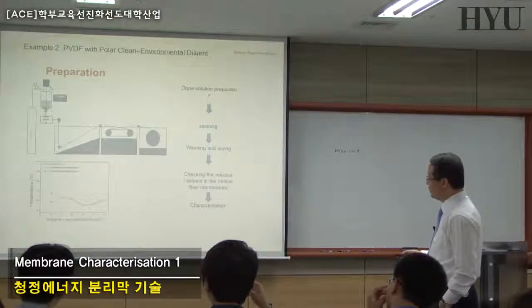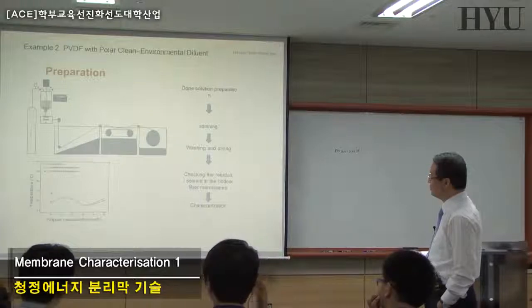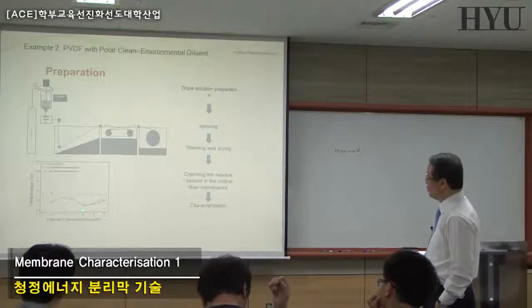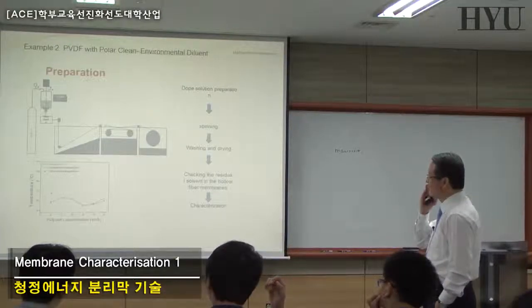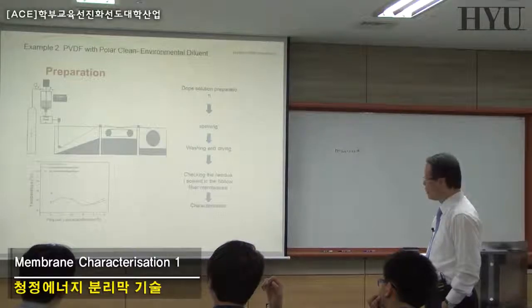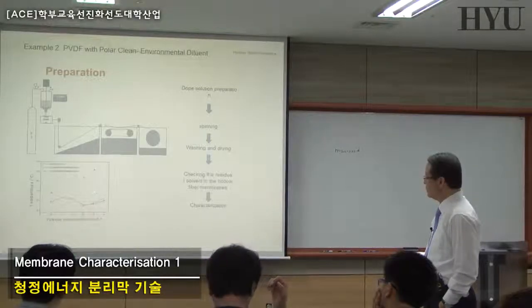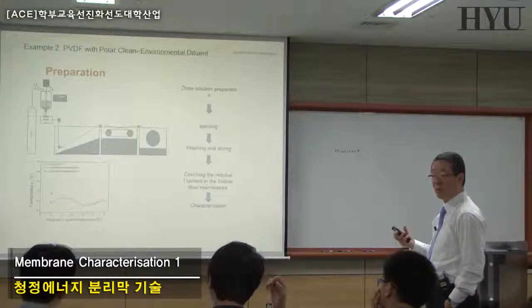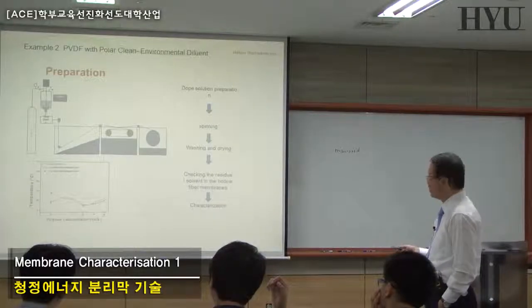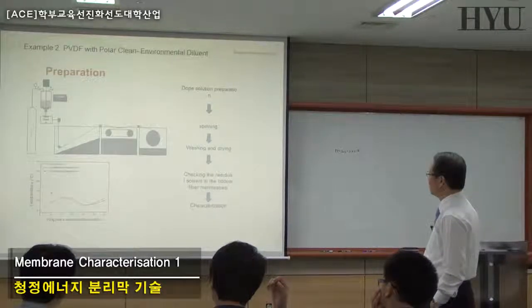This is the typical graph of the cloud point, crystal point and gel fraction temperatures, and the point where these two meet is called the monotectic point. So above these monotectic points, it's possible to make the strong gelled fiber membranes.